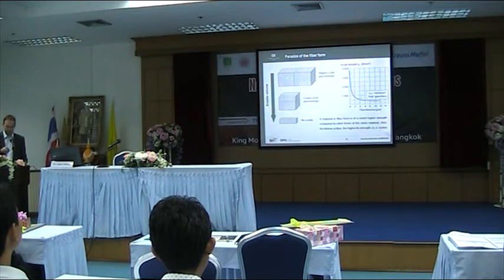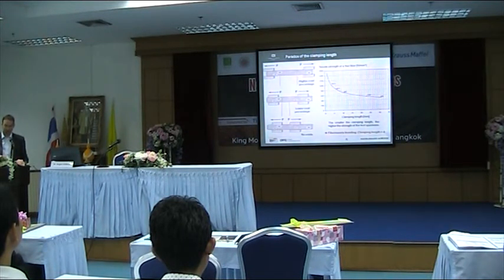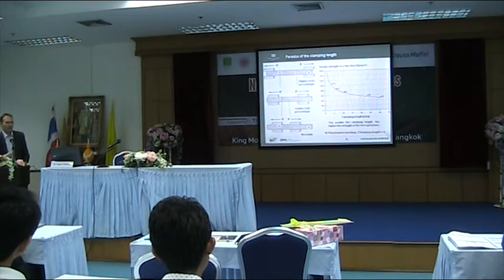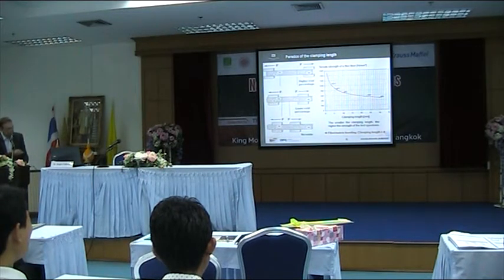Okay. So something which also rules really well for natural fibers is the fiber length, the clamping length. So maybe you know a typical tensile test, and now imagine you have a single fiber, you clamp it, and you make a tensile test. The shorter the clamping length is, the higher is the specific tensile strength of the fibers. This rule applies, for example, here for a flax fiber. You see we come to a real increase of the tensile strength when we have a lowering of the clamping length.